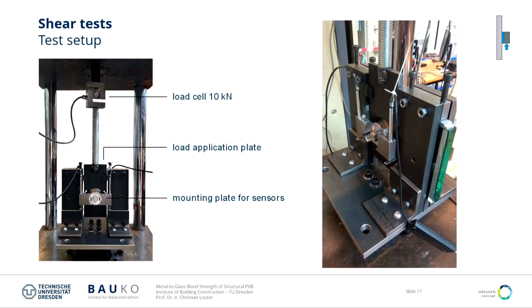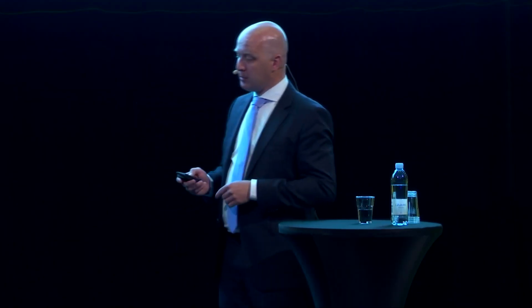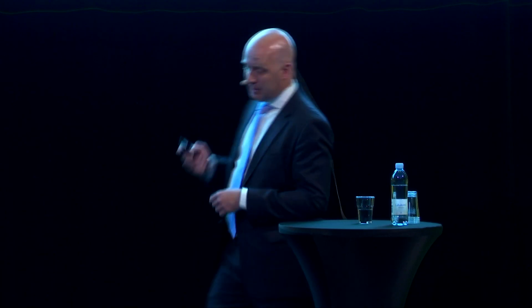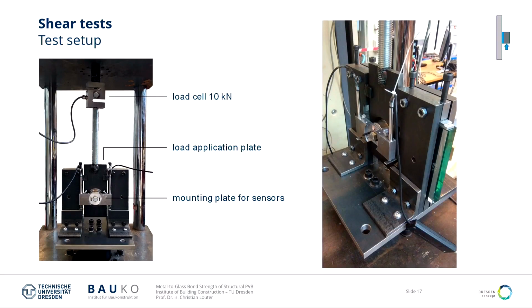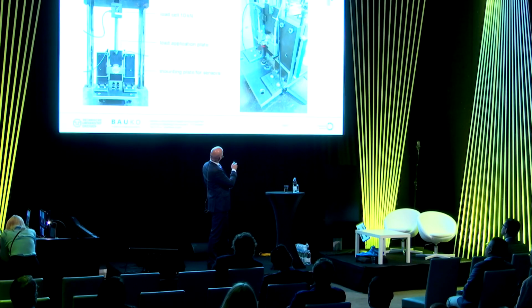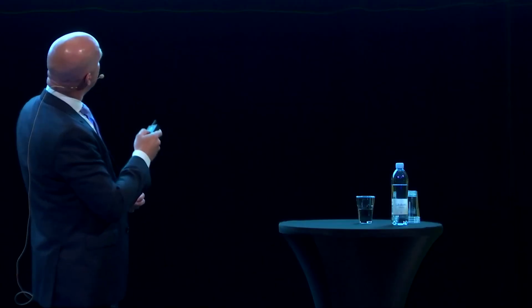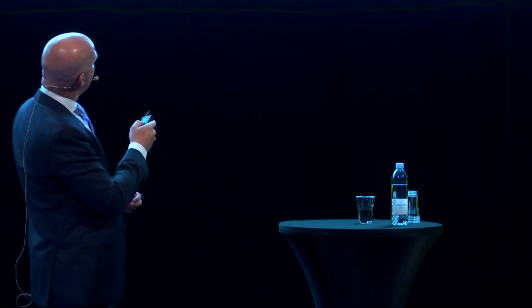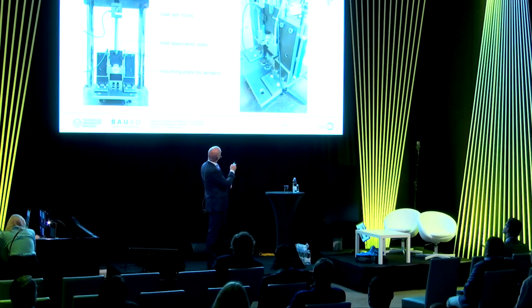And then we place it in this shear test setup. So we are going to shear the button, the steel button, from the glass piece. It's a bit difficult to see perhaps, but if we start on the right-hand side, you can see that here is the glass specimen inserted, and here's the steel button going through this metal plate, and in the end this metal plate will move upwards to shear the steel button from the glass specimen. The glass specimen will want to move upwards, but it's blocked by the setup there.